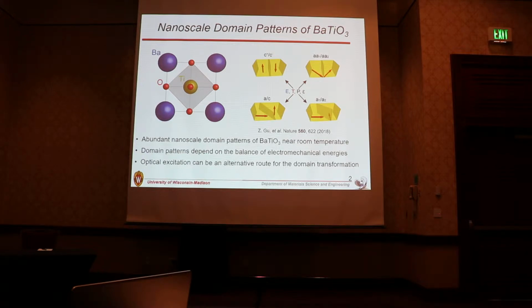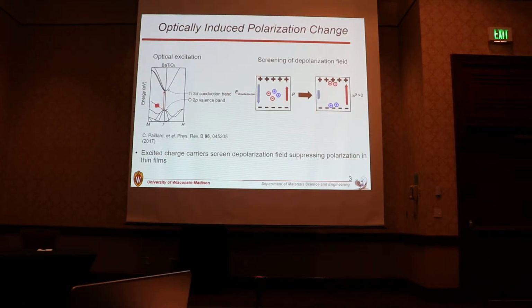So we can use external perturbations such as electric field, pressure, heat, and epitaxial strain to change the domain configurations. A recent study about optical excitations in barium titanate has proposed that the polarization can be changed by optical excitations, which means that optical excitation can change the domain configurations. The optical excitation drives electrons from the oxygen valence band to the titanium conduction band. There are several models to explain why optical excitation can change the polarization, but I would like to introduce one particular model here.